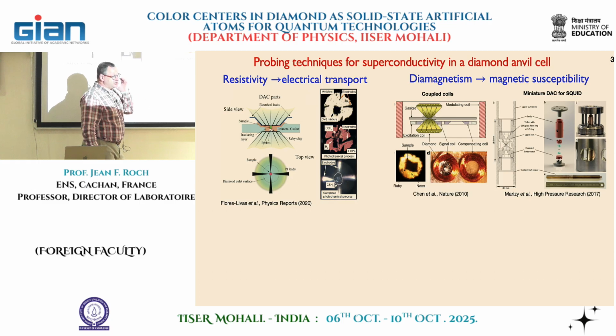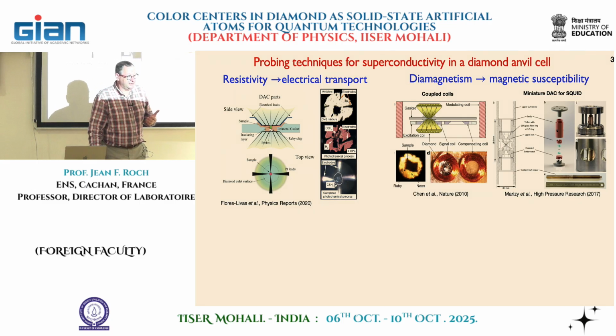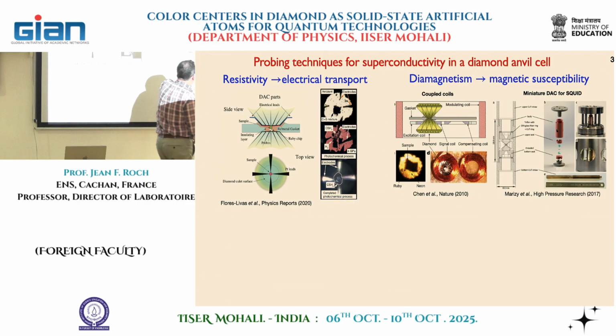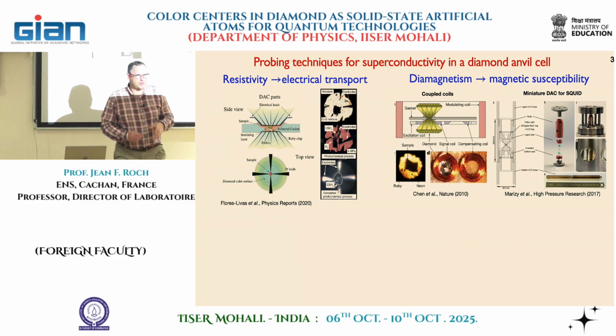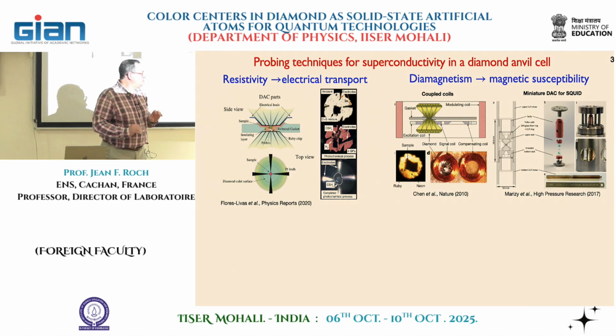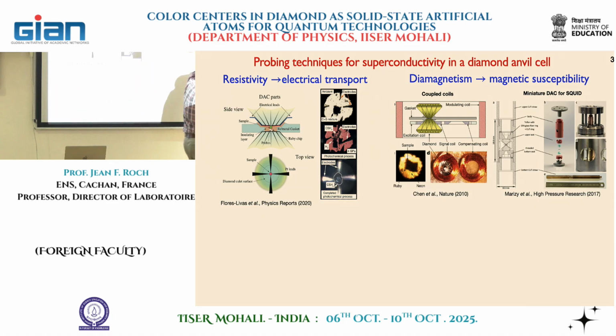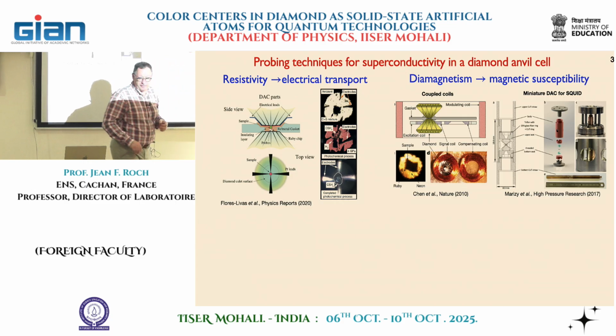The other approach is now to use the most sensitive magnetometer so far, that are SQUID magnetometers. And with those SQUID magnetometers you want now to integrate your diamond anvil cell into a SQUID apparatus. The SQUID apparatus has a very tiny diameter, so it means that you need to make very specific diamond anvil cells that are non-magnetic, and that can be integrated into this system. And that's, again, very, very challenging.